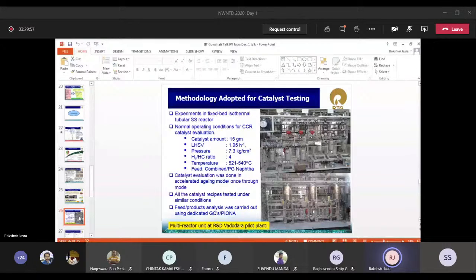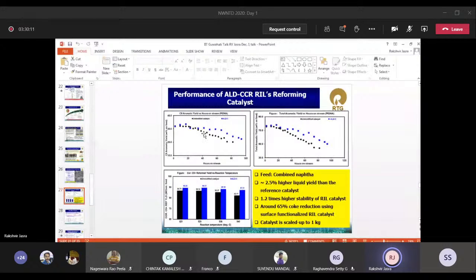So we brought the naphtha, which has all the impurities in it, which is actually used in the plant. We have used the naphtha, and using this, we have shown... Now you see this number, you just see the blue line and the black line. Black line is without the atomic layer deposition, and blue line is with atomic layer deposition. You can see the activity and the stability of the atomic layer deposit catalyst is higher compared to the black line.